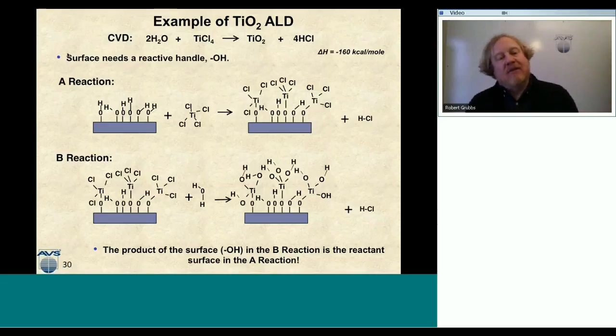The first thing that I have to assume about this is that for my A reaction, I've got this hydroxylated surface. I've got this OH saturated surface. So when I come in with titanium tetrachloride, I can react 1 or 2 of those chlorine atoms with the hydrogen of the OH on the surface to make an O-titanium bond and give off HCl gas, leaving you with a chlorinated surface. That's what happens in the A reaction.